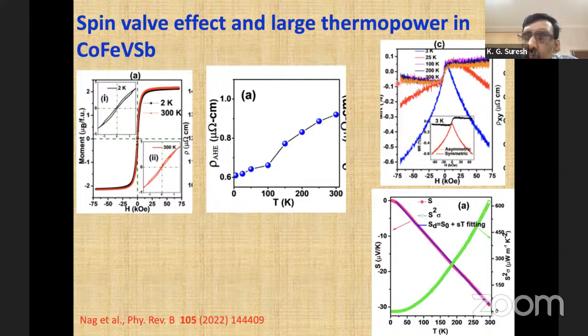This has been reported in very few systems, where the magnetoresistance changes sign as the field is changed. This is a very usual spin valve feature that is expected, but that is generally seen in the case of artificial multilayers and so on. Here there is no multilayer. It's a single bulk polycrystalline material, but we are seeing features corresponding to that. So this is very interesting.